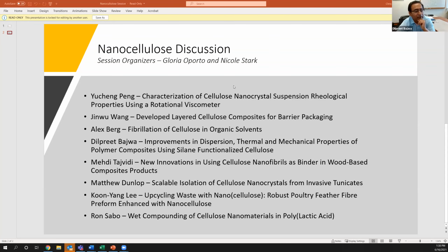So, Mehdi, I have a question that's kind of two-part. One is, what percentage of nanofibrils do you add to these wet boards, and how do you make sure they are dispersed? Well, I can talk about dispersion first. Dispersion is actually very easy. You have a lot of water in the system, and as long as you have water so that the wood particles get wet, you get very good dispersion. I don't see any issues around that.